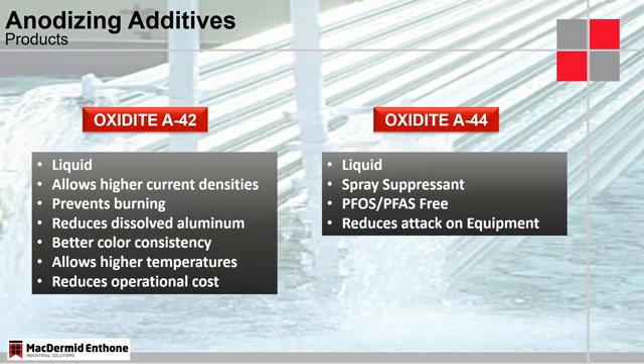The Oxidite A44 here, again, most of the additives we sell for anodizing are liquids for easy handling and additions to the tank. This is a spray suppressant, and it's not a wetting agent as most people are probably used to. This is a completely PFAS-free product, so that really complies with all the legislation out there at the moment. Because it forms a very nice thin layer of foam on the surface, and it reduces the spray, it helps significantly with reducing attack on any sort of plant and equipment.